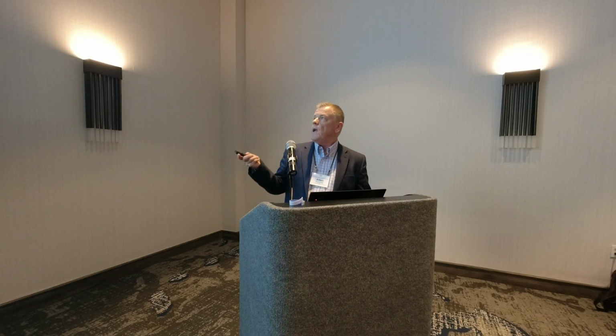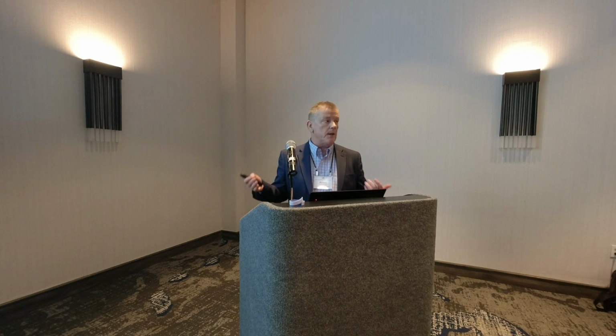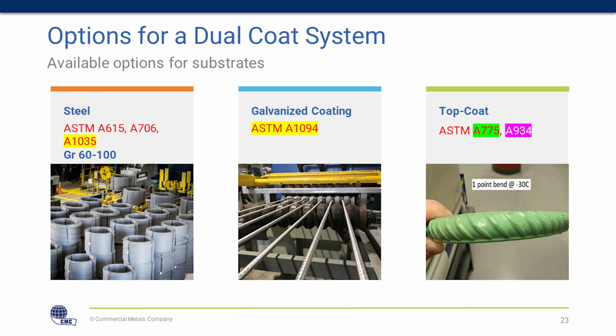But this can be applied to all these substrates. You can apply galvanizing to any grade steel as well. And so you got these substrates over here. This is more of an intermediate substrate. And so there's an ASTM standard that's A1055, which is where you would apply the fusion bonded textured epoxy coating